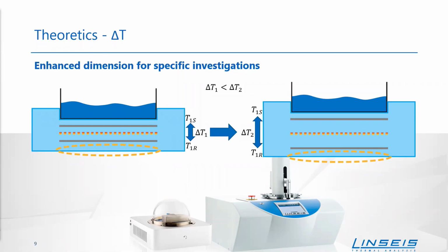What we do now is we change the space between the heater and the temperature sensors. Or more important, we change the distance between both of these sensors. As you can see, the heater itself is still in the middle, but the space between reference and sample sensor is much bigger. And this leads to a higher temperature gradient because, as you know, if there's some reaction of the sample, for example melting, it needs some heat because it's an enthalpic transition. This way we can see a temperature change between these two sensors, and this is what we detect.